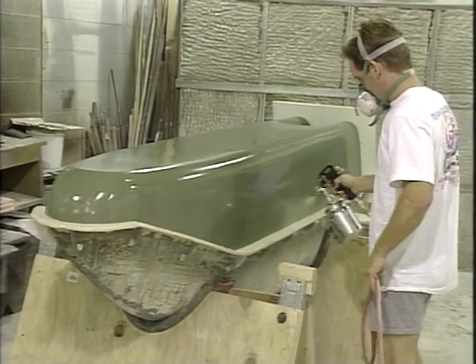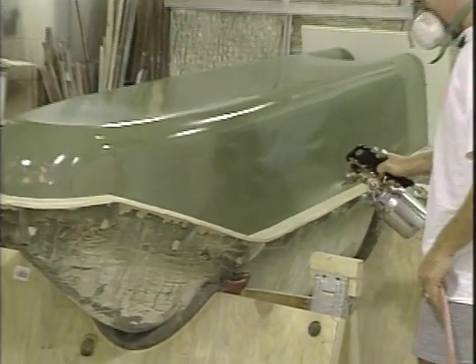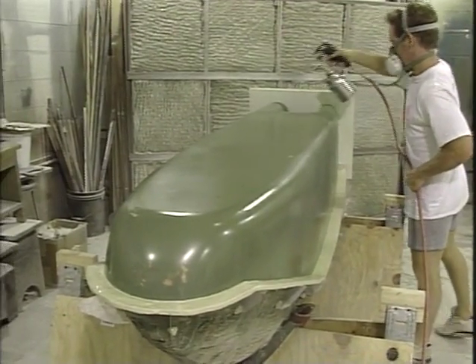Since the plug was already waxed, it was ready for PVA. The clay shelf and the entire exposed half of the plug were then sprayed with PVA. 3 light coats were applied to the highly waxed surface and allowed to dry. The mold surface should appear uniform and dry before continuing to molding. At this time, the lower mold was constructed off camera and removed from the plug. Later in this video, we will document the construction of the top mold in detail.